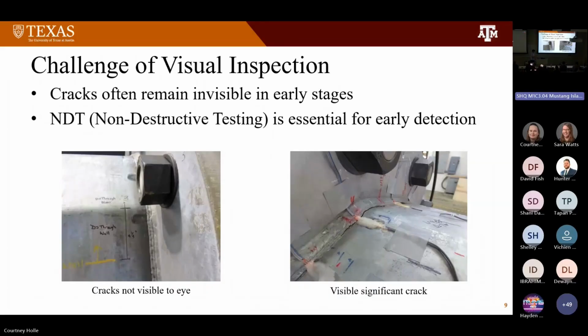So despite these clarities, there is still a challenge. Here what we can see is both images have a crack, but on the right side, the crack is clearly visible, but on the left side, the crack is not visible. The problem is cracks often remain invisible in early stages. So by the time a crack is visible, significant damage may have already occurred. So that's why early detection is important, but it is difficult. And for that, non-destructive testing, NDT, is essential.